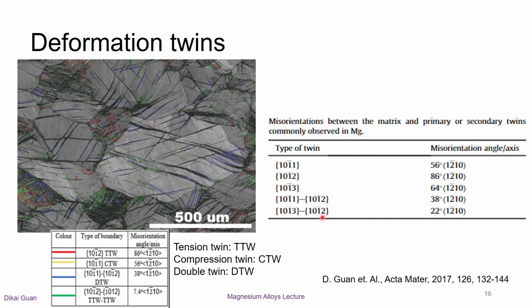It is now very easy to use optical microscope, SEM, EBSD, and TEM to observe and index deformation twinning types in deformed magnesium samples. For example, in this EBSD image, TTW is short for tension twin, CTW is short for compression twin, and DTW is short for double twin. The different twin types were color-coded according to their unique disorientation angle-axis in this EBSD special grain boundary map. For example, TTW is color-coded in red and has a misorientation angle-axis of 86 degrees along the <11-20> direction.